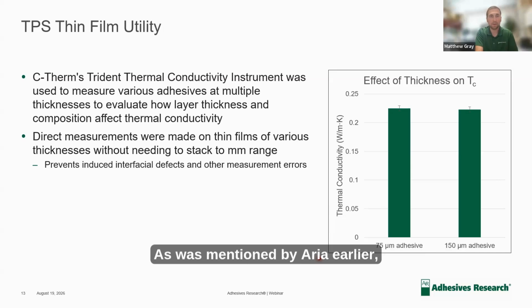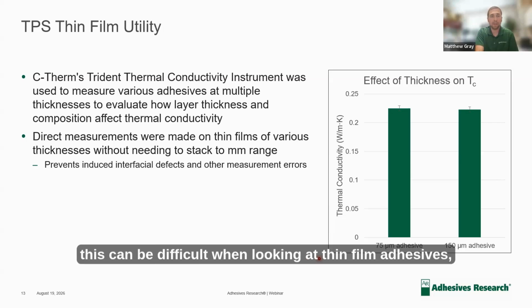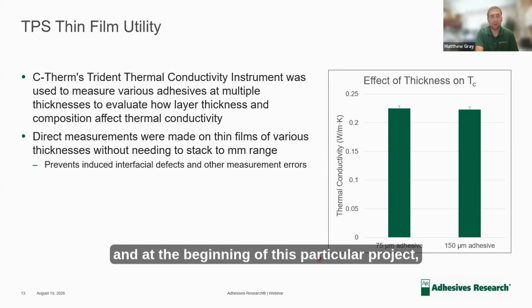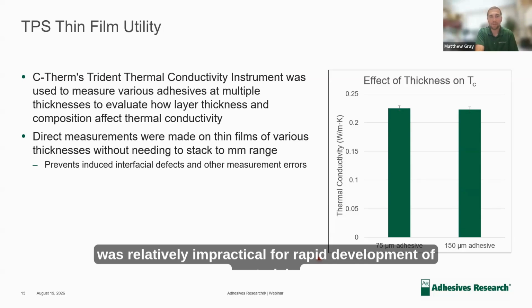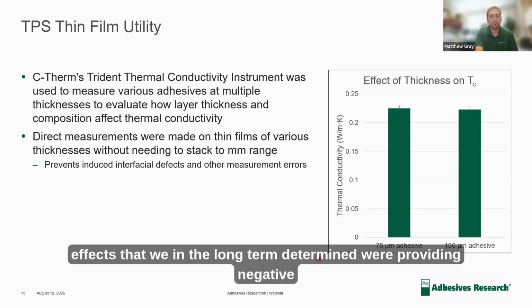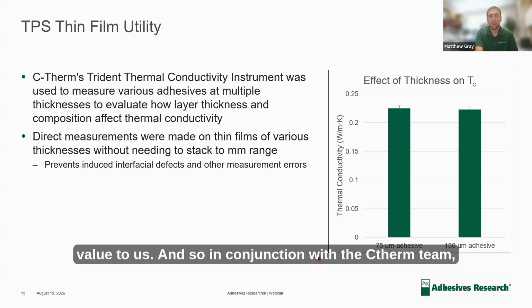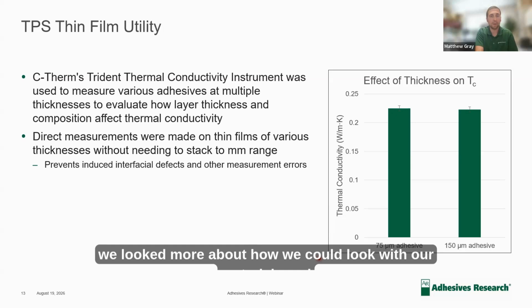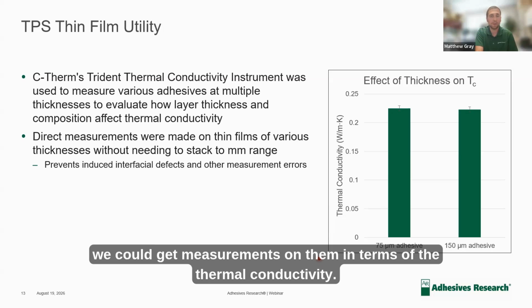As was mentioned by Aria earlier, this can be difficult when looking at thin film adhesives. And at the beginning of this particular project, we did exactly what he talked about. We were layering up adhesives constantly to get very thick films so we could measure them, which, while it worked in the short term, was relatively impractical for rapid development of materials, and also induced a lot of unnecessary interfacial effects that we, in the long term, determined were providing negative value to us. And so, in conjunction with the C-Therm team, we looked more at how we could test natively made thin film materials and see how consistently we could get measurements on them in terms of the thermal conductivity.